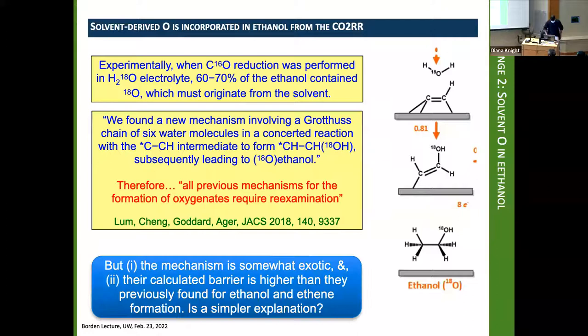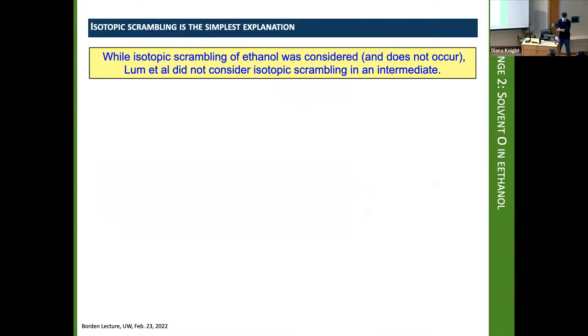So on the other hand, this Grotthuss chain of six water molecules is a bit exotic in a bulk solution of water. And also the calculated barrier was a bit on the high side. So we wondered if there might be a simpler explanation, in addition to simply wanting to defend the mechanism. So what about isotopic scrambling? Isotopic scrambling is a good possibility in an intermediate. The experimental study, of course, checked for isotopic scrambling of ethanol and showed that didn't occur. But just because it doesn't occur in the product doesn't mean that it couldn't have occurred in an intermediate on the way to the product.